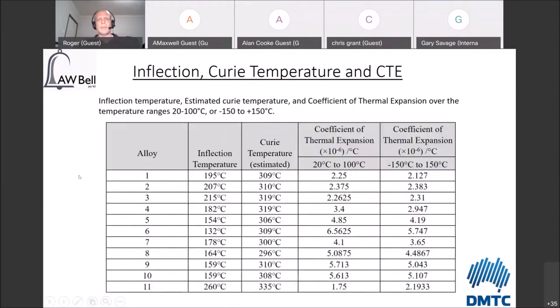And the coefficient of thermal expansion that you can see here, this is just actually the numbers. So we're looking at the coefficient of thermal expansion between 20 and 100 degrees Celsius, and this is quite often how it's referred to in literature. And then minus 150 to plus 150, which is what we're interested in. Now you can see between 20 and 100 degrees Celsius, on our preferred alloys, these ones here, you're around about that 2.3 mark, and that compares to the wrought material at about 1.8.